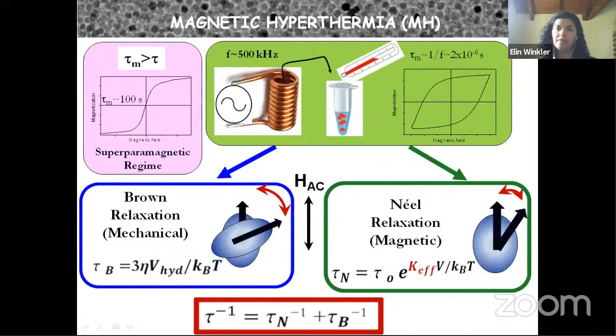The other mechanism is the magnetic mechanism, or the Néel relaxation mechanism. In this case, the nanoparticles are fixed in space and only the spins of the nanoparticle, only the magnetization of the nanoparticle, rotates. So in this case, as the magnetic nanoparticles are fixed in space and only the magnetic moment will rotate, the relaxation time will depend on the magnetic parameters.